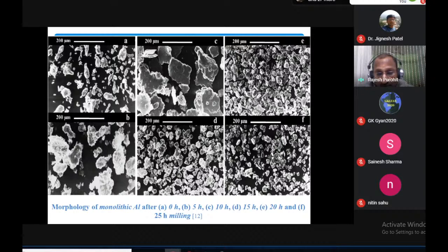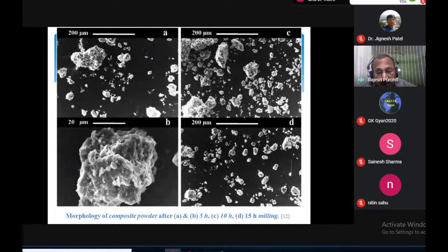In between we take a sample at an interval of 5 hours, and the morphology of the powder particles is seen using an SEM, a scanning electron microscope. At an interval of 5 hours the micrographs are shown. The next figure also shows a micrograph of aluminum with nano alumina particles at an interval of 5 hours of ball milling.